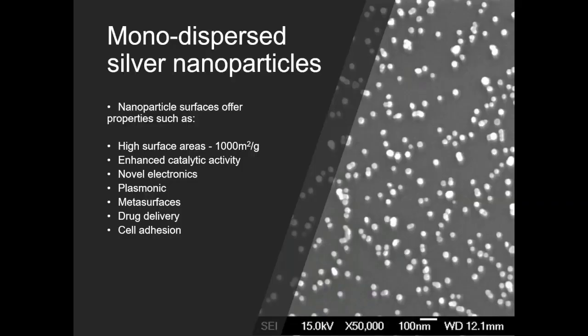Really, so on this picture here, we're using our physics technique to deposit very nice looking nanoparticles. You can see the bottom scale there. These are sitting at about 10, 15 nanometer diameter. One thing I should say, because we're using our physics process to deposit these, we get really clean semiconductor type deposition purity, as opposed to some chemical routes, which are what most people use now. You tend to get the particles bunching up and some contamination in there as well.